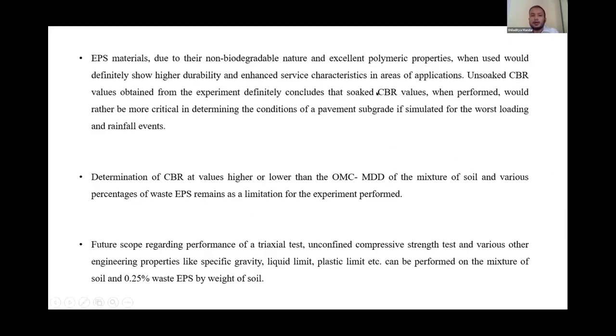So we've basically operated our testing using the unsoaked methodology. And a future scope always lies here: it would be extremely critical in determining the conditions of a pavement subgrade when performed for a soaked CBR test, because that would actually simulate the worst loading and rainfall events. Okay, so the determination of CBR at values higher or lower, that is the dry side or the wet side of the OMC-MDD curve, with various percentages of waste EPS with our soil, can also be tested out, and that also remains as a limitation of this experiment performed.